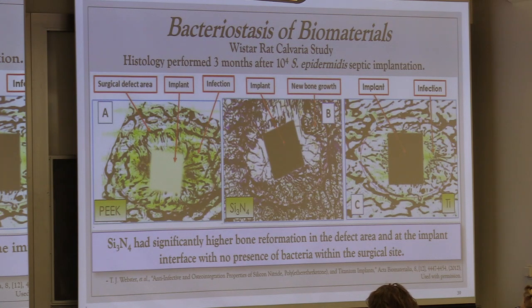But before they implanted them, they actually contaminated the implant with Staph epi. And what the investigator here, this is done independently, wanted to see was, is there any difference between these three biomaterials? And yes, there is significant difference. The yellow stain here that you can see is actually latent infection that is still present around the implant at 3 months post-operative. There is significant infection also, but less around the titanium implant, but essentially no infection present around the silicon nitride implant. Now, it is true that the presence of an infection in an implant will hinder osteointegration, which is the purple stain that you see here, but there is significantly more growth around the silicon nitride than either of the other two implants.